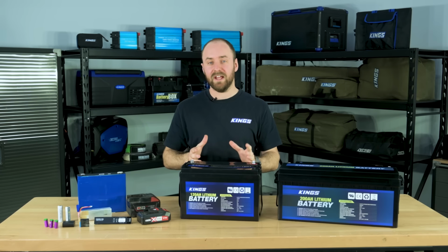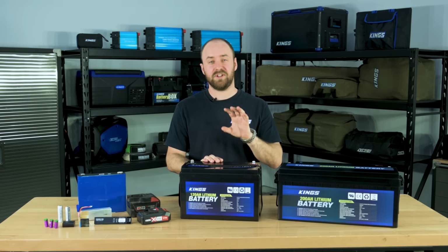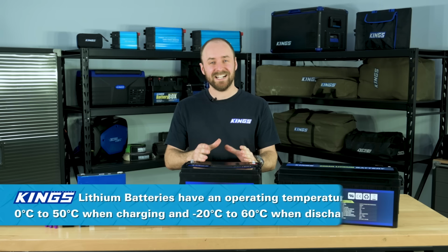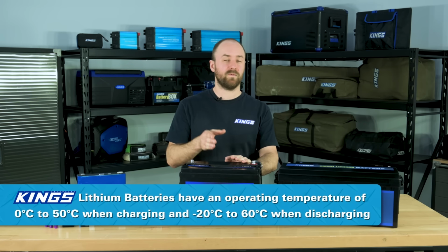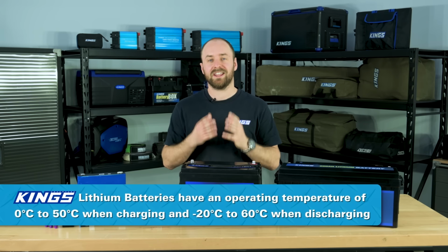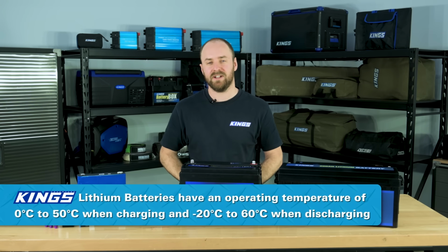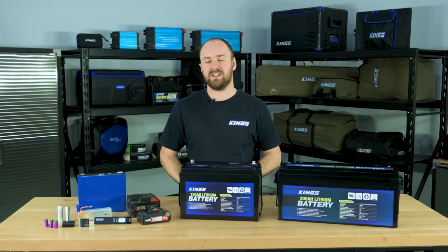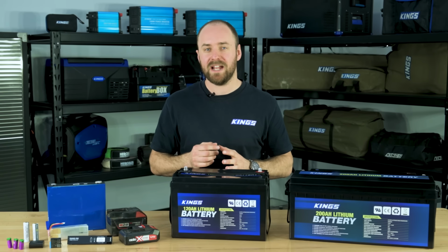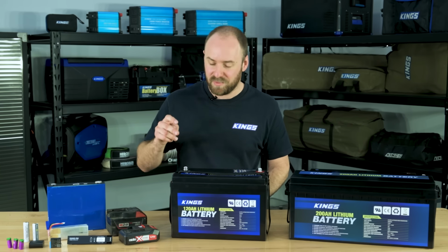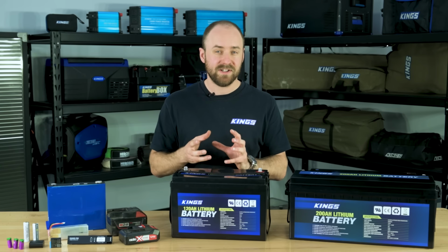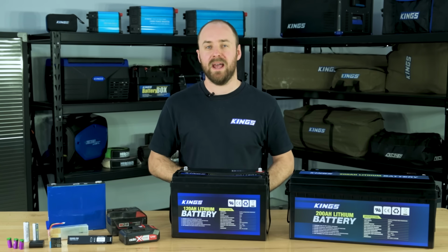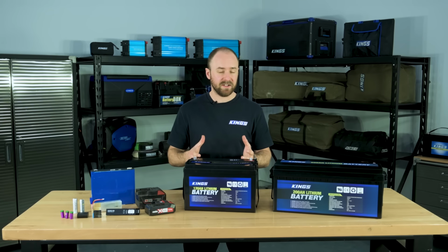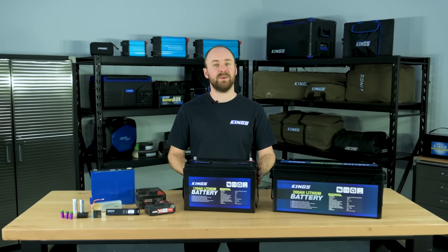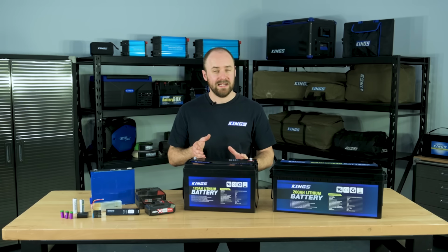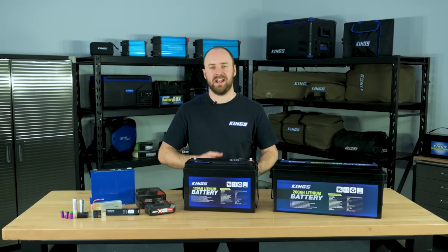At the other end of the scale, your lithium iron phosphate battery shouldn't be too cold. Charging a lithium iron phosphate battery below freezing, or 0 degrees Celsius, can actually cause irreparable damage. Now your BMS should prevent this, but if you did force charge the battery, it can cause the lithium to plate the anode. That increases resistance and permanently drops capacity of your battery. So if you're camping in the cold and your battery doesn't seem to be working or taking any charge, it could be that the BMS has disconnected it to protect it.